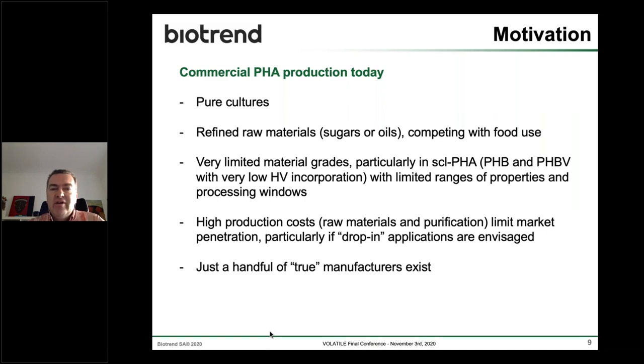So today, the commercial production is exclusively or mainly performed using pure culture and using refined raw materials like sugars and oils. And there are very limited grades out there, particularly for the shorter chain polyhydroxyalkanoates, which comprise PHB and PHBV. The incorporation of valerate in this copolymer is very low, up to 3% only. So ultimately, the mechanical properties of the commercially available PHBV are not that different from the homopolymer, which is a problem because these materials tend to be extremely brittle.